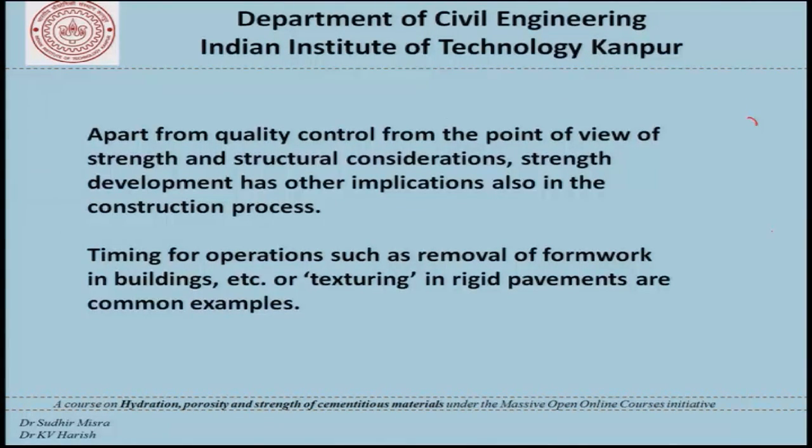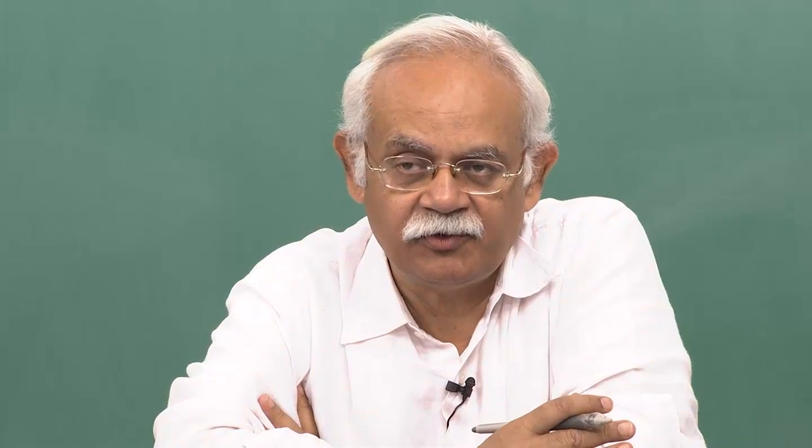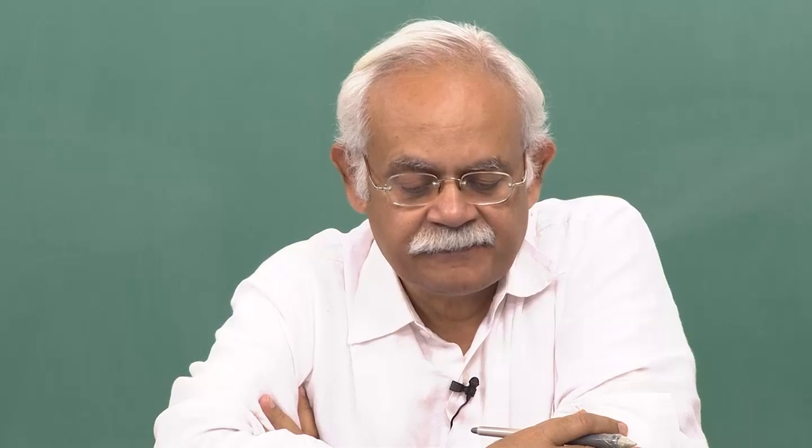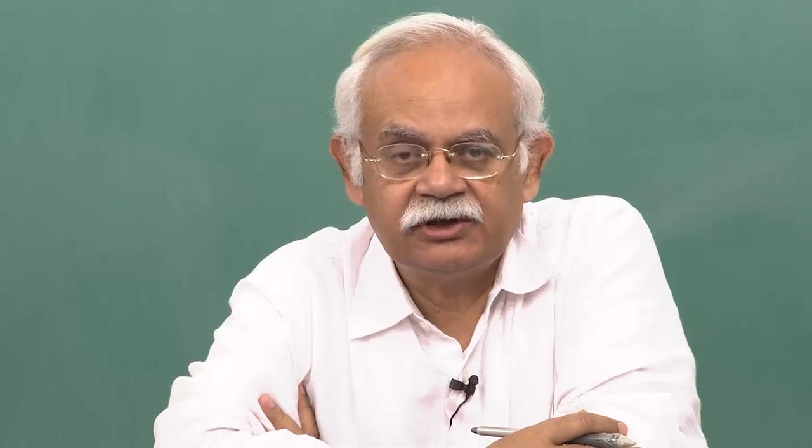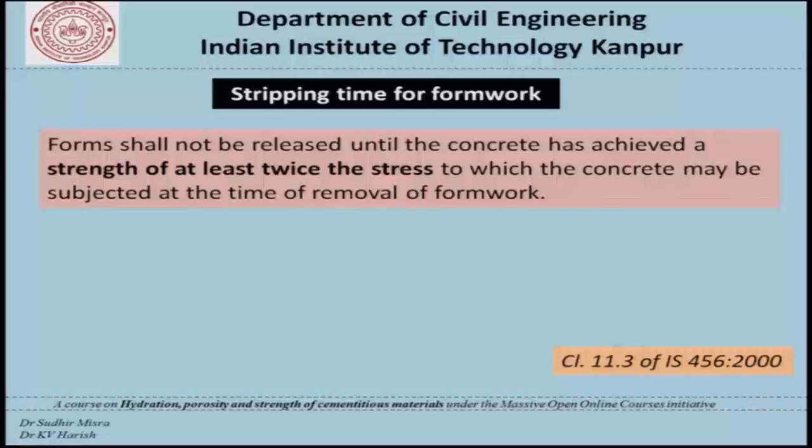And of course, in buildings we are concerned with that because we want to recycle the formwork and we want to move forward with the construction process. So at what time should the formwork be removed? As far as the Indian standards are concerned, 456/2000, when it talks about the stripping time for formwork, which is the time for removal of this formwork, it says that form shall not be released until the concrete has achieved a strength of at least twice the stress to which concrete may be subjected to at the time of removal of formwork.